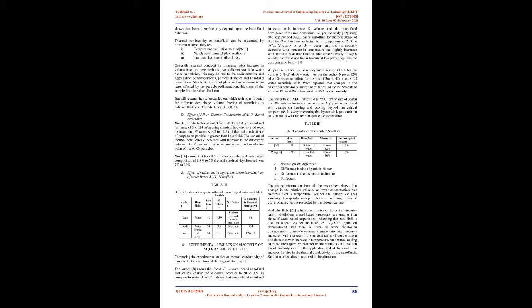Das showed that for 60.4 nm size particles and volumetric composition of 1.8% to 5%, thermal conductivity enhancement observed was 7% to 21%. Experimental results on viscosity of Al2O3 based nanofluid were also studied.